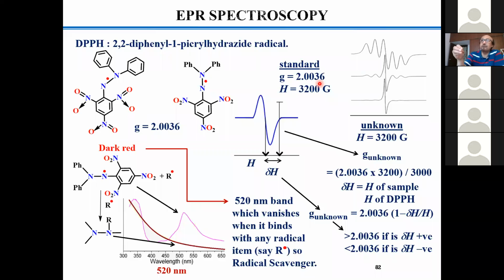Okay, in the SOMO, what is the singly occupied molecular orbital. Okay, it's not a unidimensional SOMO. If it is 2.00 something, the SOMO is 100% composed of the radical. If it is 2.07 or 2.06 or 2.09, that means you have roughly 90% radical composition at the SOMO, and at least 10% metal contribution is there. But if you get 2.1, the first digit, 2.1, 2.2, 2.3, that means you are slowly moving from radical to metal. So your metal participation in the SOMO is progressively increasing from 10% in the previous case to 30, 40, 50, 60, 80, even 90, even 100 at one point, the purely metal-based signal.